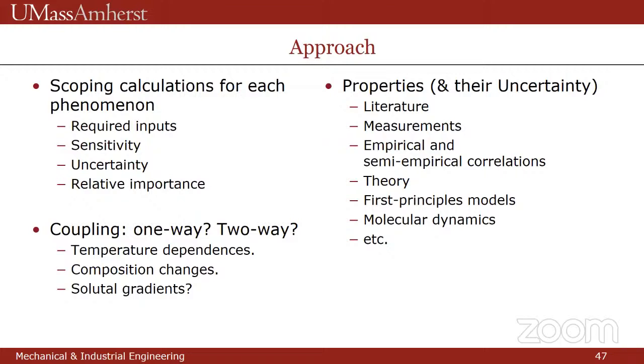So an approach for dealing with these really complicated phenomena: first, you start with scoping calculations. You decide what matters for me today. And so you go from a list of maybe 100 things you might want to put in to the 5 that have to be in for the answer to mean anything. And you do this through sensitivity and uncertainty analyses. The scoping calculations also tell you about one-way versus two-way coupling. So in our magnetohydrodynamic calculations for the levitated drops, you can look at a single dimensionless group, the magnetic Reynolds number, that tells you the magnetic field drives the flow, but the flow is too slow to change the magnetic field. So that's a one-way coupling, and you're done. You don't build the reverse coupling.